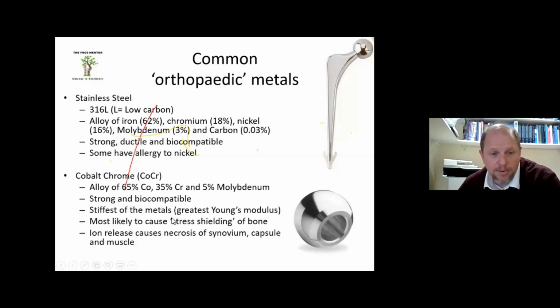And in fact, some implants like the CPT implant, which is a hip implant, a polished tapered stem, is made out of cobalt chrome, and it's said to have a slightly higher periprosthetic fracture rate than the Exeter, which it looks very similar to, but they're made of different materials. The stiffness of the cobalt chrome could be playing a factor in that. And the other key thing that gets asked about cobalt chrome is what if you use it in something like a metal on metal hip replacement? Obviously you get a lot of chromium and cobalt ions, and that causes necrosis of the tissues around and can cause systemic problems as well.